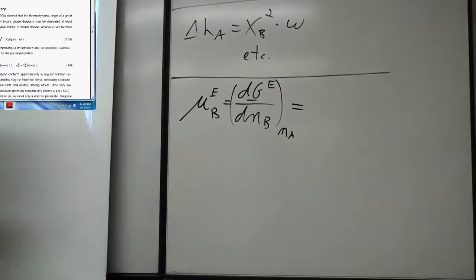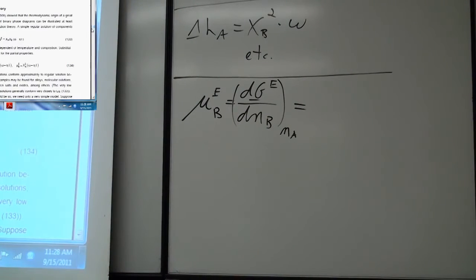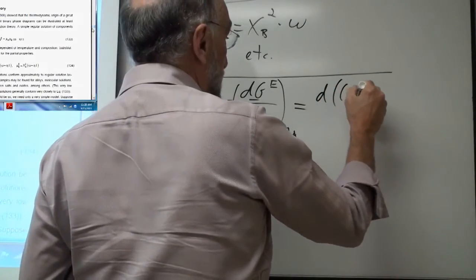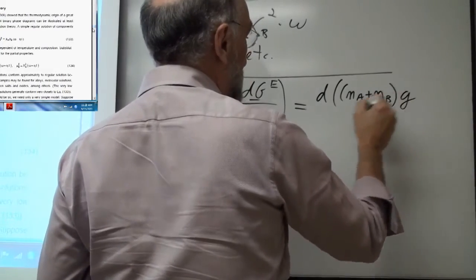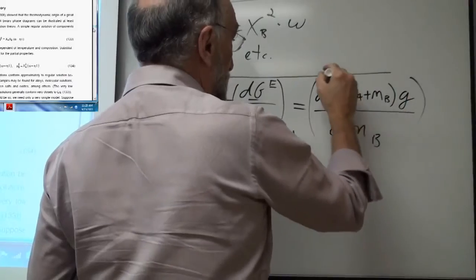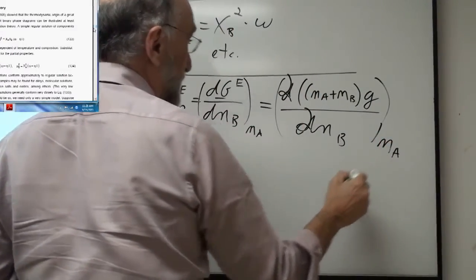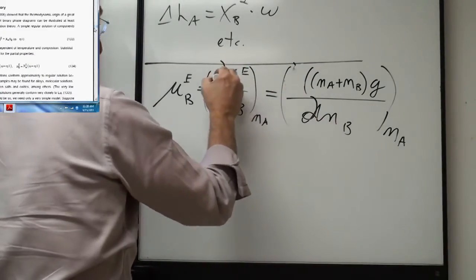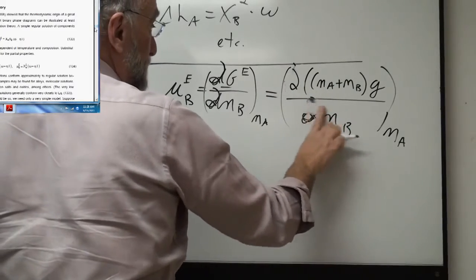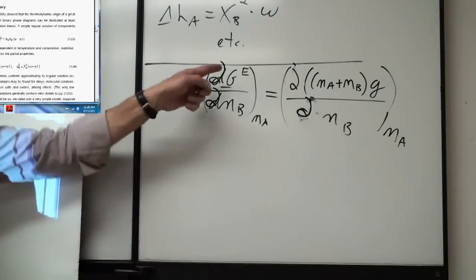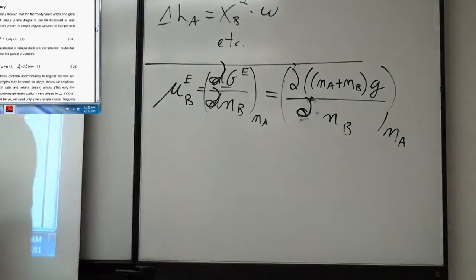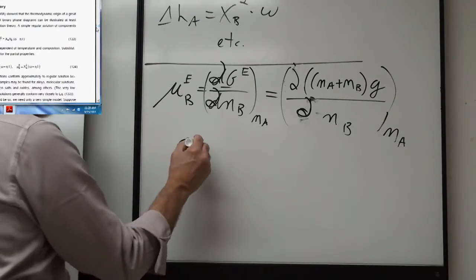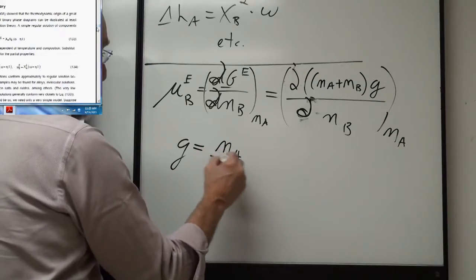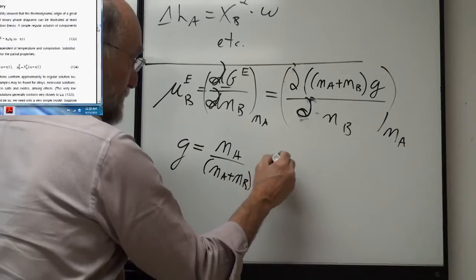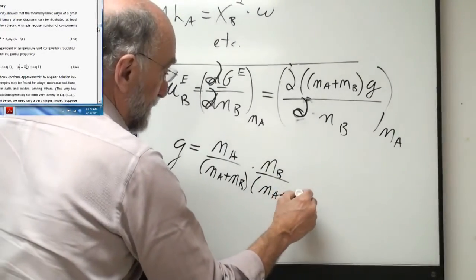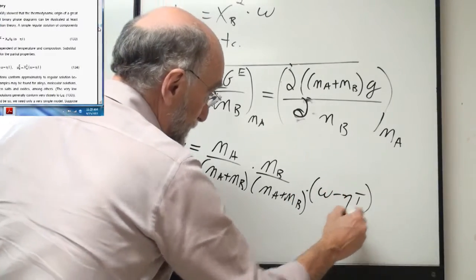But what you got to remember is that the G up here is an uppercase G, so that is the total Gibbs energy in joules, not joules per mole. So this would be d of (Na plus Nb) g, dNb, a partial derivative, when Na is constant. So we're writing the partial derivative. You're taking a partial derivative of the total excess Gibbs energy with respect to Nb, keeping Na constant. And where g then is equal to Xa Xb, so Na over Na plus Nb times Nb over Na plus Nb, times omega minus eta T, which is a constant.